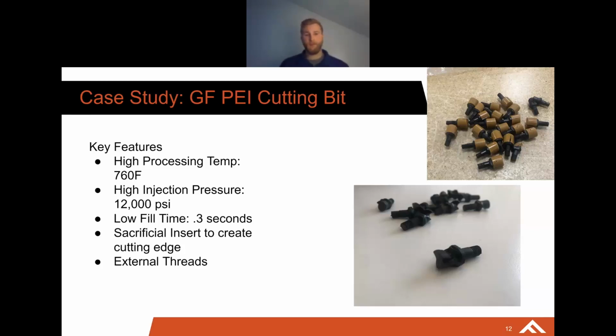The other thing is we really broke all of our rules. So our high injection pressure breaks our 10,000 psi limit, which we usually set for ourselves, and then the low fill time. So I was running at machine maximum speeds here in order to get this to flow. As you know, if any of you guys have molded with ULTEM before or anything else really high temperature, you're running with a mold that's 350 to 400 degrees Fahrenheit.